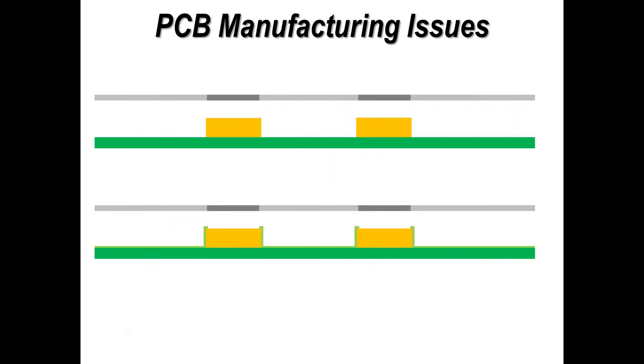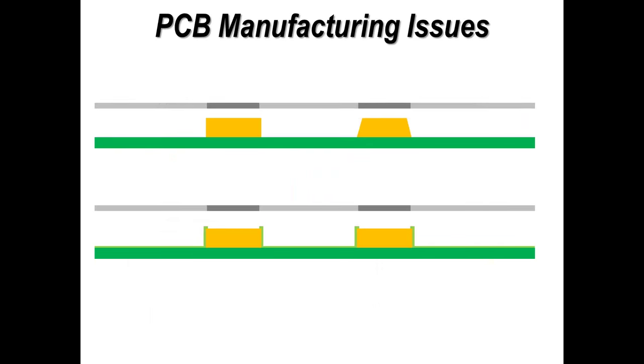Now, if we're printing onto very, very small pads, as is starting to become the norm in our industry, then again, the basic process is exactly the same. But one of the things, again, to look out for, particularly when you go down to 0201, 01005 and smaller, is that the aperture really wants to be not larger than the pad size.